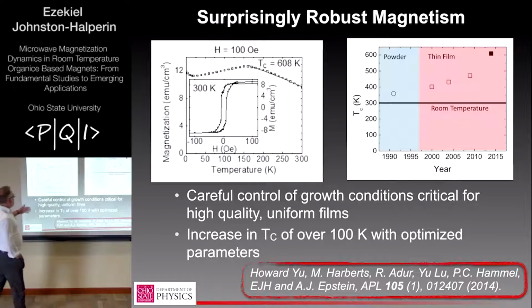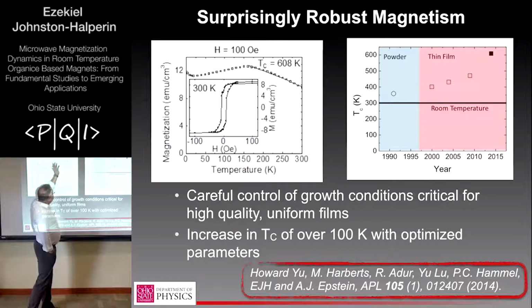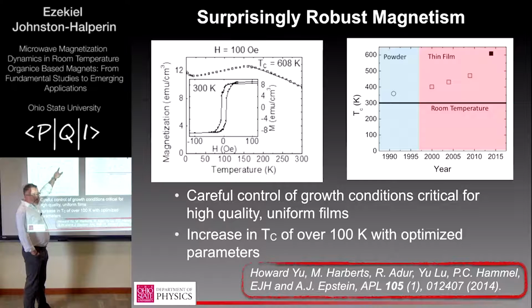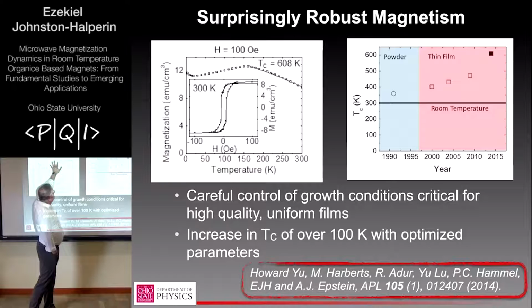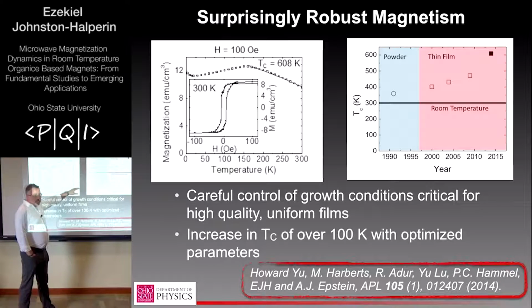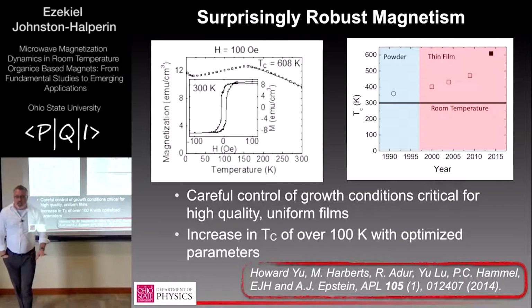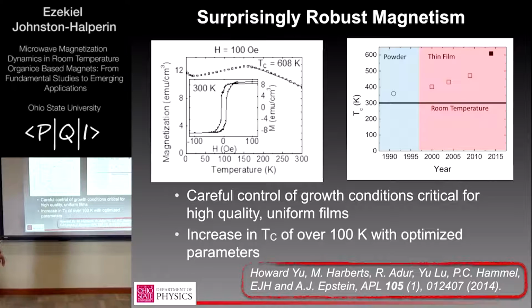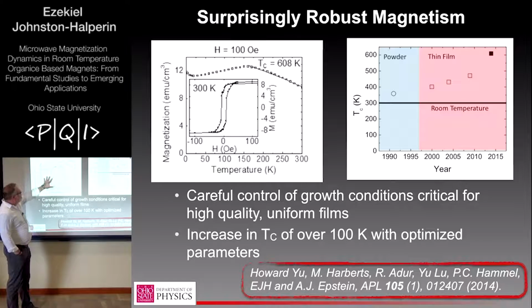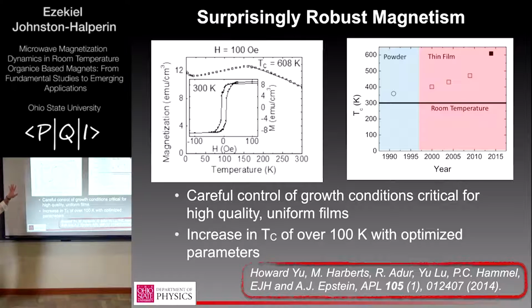And extrapolating to extract TC is a little bit tricky because there's a low temperature magnetic phase here, which limits our ability to fit reasonably to low temperature. So if you fit just this region to a Bloch law, you get an energy scale of about 600 Kelvin. You'll notice at room temperature, we have pretty sharp switching. We have pretty high remanence. It's pretty well saturated. In fact, this curve gets worse at low temperature, which is interesting.